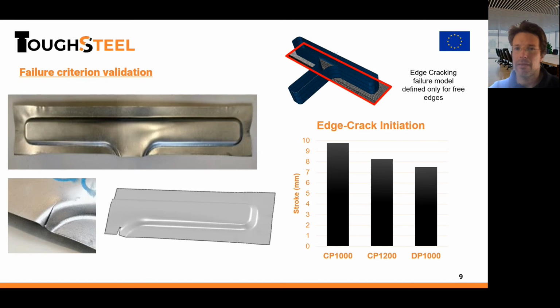Next one. Here again, using the same tooling in a different configuration, changing the blank dimension, we also obtain similar results. It's important to remember that we use our model in conjunction with FLC: our model for the edge cracking, FLC for what happens in the bulk material, and we use the essential work of fracture only in the edges. With this model, we have a good tool for material selection. And in this case, we analyzed these three materials, the CP and DP.